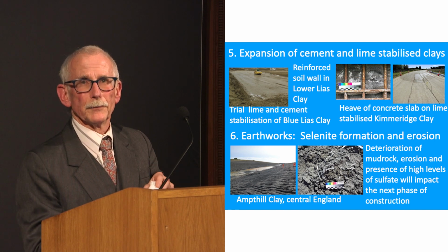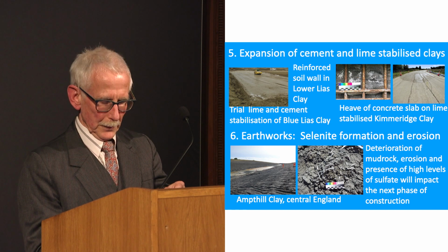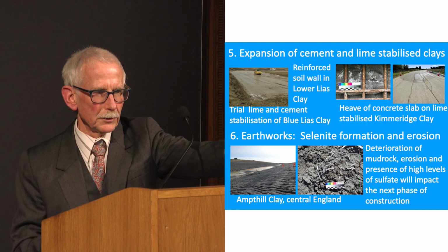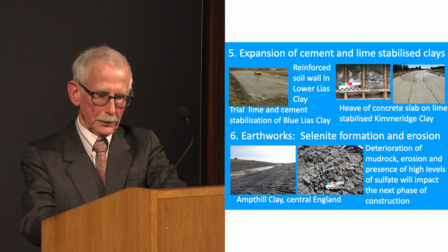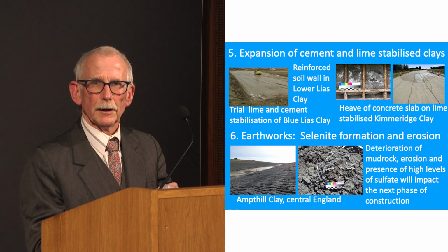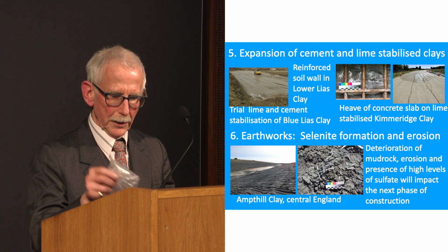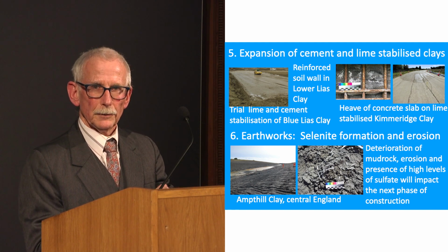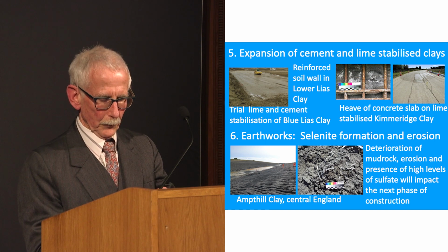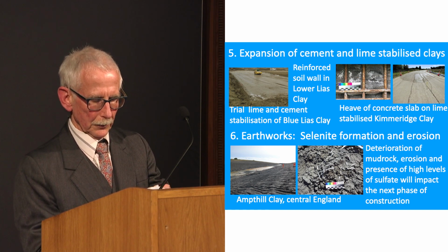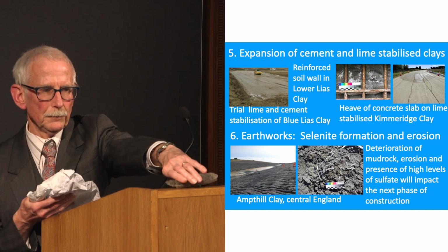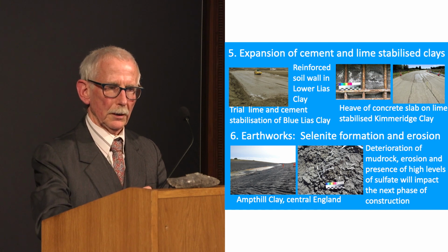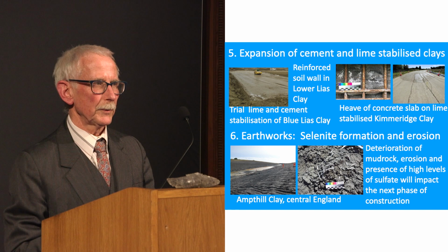The slide in the centre at the bottom shows the selenite crystals, which I'm just unwrapping here, kindly lent to me by Morris. We can see that they are forming in this clay due to pyrite oxidation processes. The cutting that you see there, where the clay is very soft and greatly affected by weathering action, softened over a period of about a year with the growth of these rather splendid crystals.